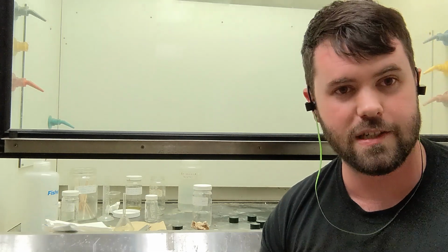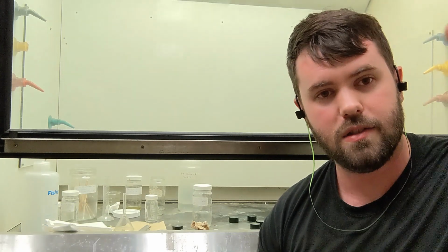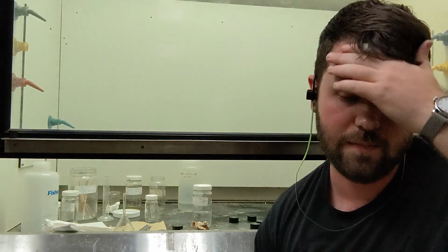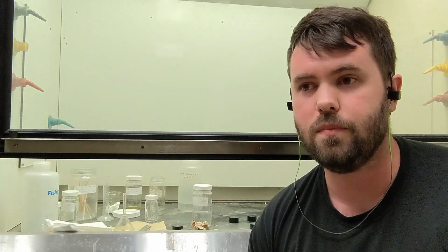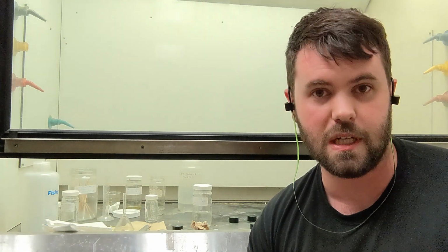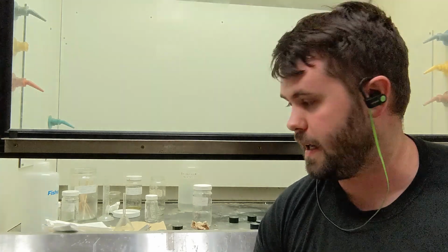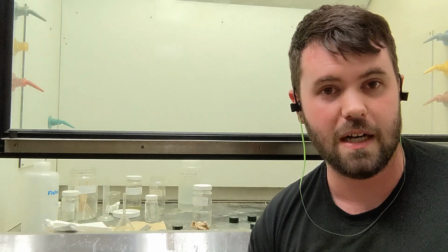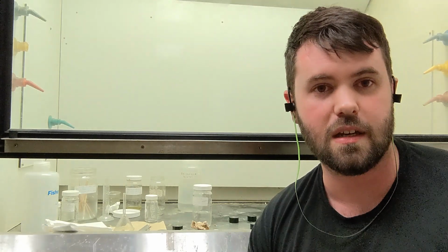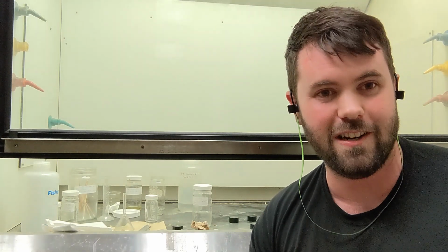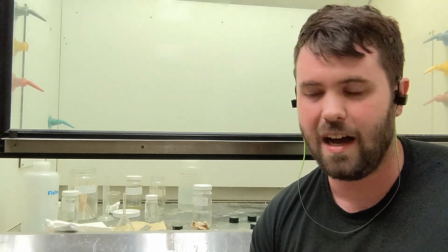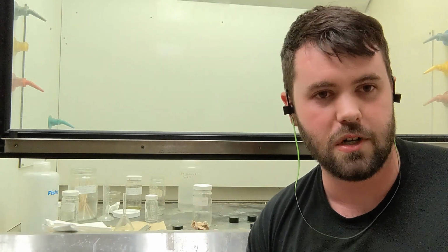But if you over-etch, the problem is you have to go back to our automated polishers and do the last like 2 steps again. You have to repeat, you have to remove material. So it's better to under-etch initially than over-etch. But again, for steel, pretty quick, about 10 seconds, and then you wash it off in the sink. I'm gonna go check to make sure I did an okay job, and once I did, I will return and we will go to the microscope room.